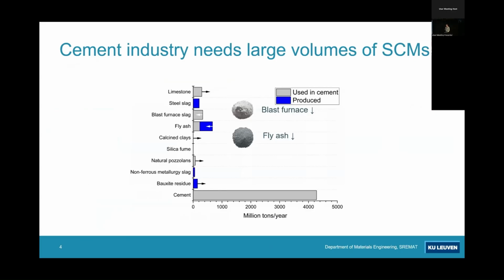So we need a lot of supplementary cementitious materials to replace Portland clinker, and there are quite some options out there. However, the most popular options, blast furnace slag and fly ash, are decreasing. Blast furnace slag is probably decreasing due to the electrical transition. The processes are being changed, for example, to electric arc furnaces. Fly ashes are decreasing because we don't combust that much coal. So we need new materials that can replace Portland clinker, and in very high volumes, because the CO2 emissions are unavoidable from Portland clinker production. So the more we can replace, the better.